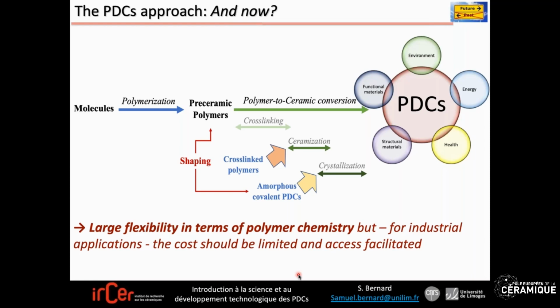However, to reach large applications, the chemistry must be simple. Sometimes it is really complex. I didn't mention this, but I think I mentioned, you work under inert atmosphere, argon, nitrogen, or reactive atmosphere, ammonia, but I mean without oxygen, because if you use oxygen, you form oxide. And this increases the cost of these materials. So for application, we should simplify the chemistry, and we should prepare polymers that can be stable for a short period in air. This is really possible, and this opens their application in industry.